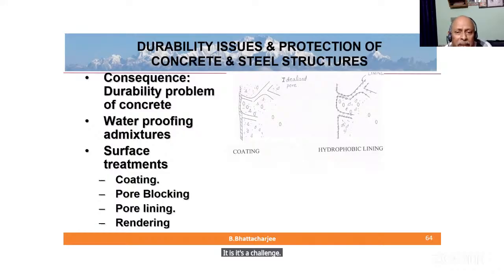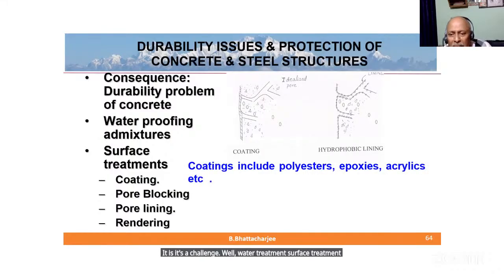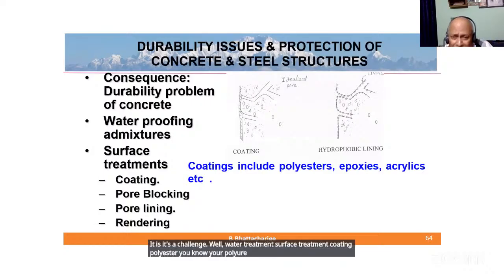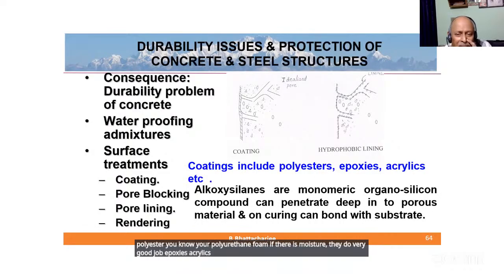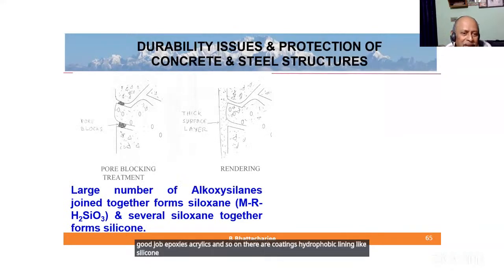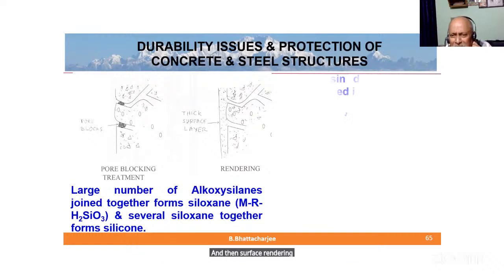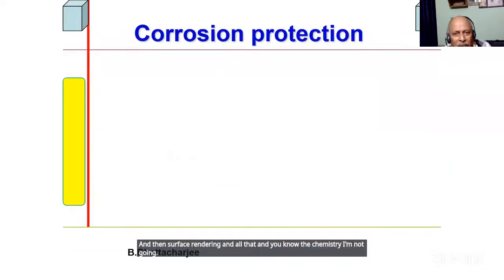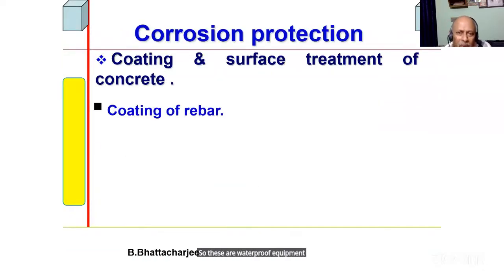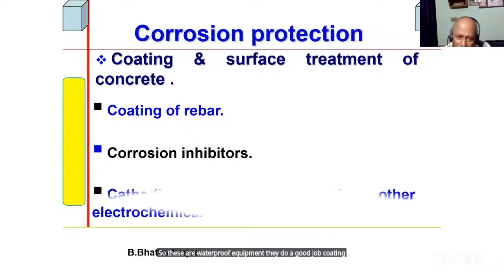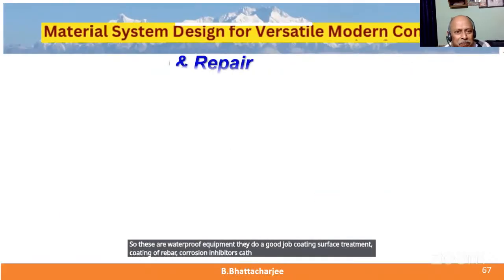Well, water treatment, surface treatment, coating, polyester, polyurethane foam. If there is moisture, they do a very good job. Epoxies, acrylics, and so on. There are coatings, hydrophobic lining like silicone, pore blockers. Even polyurethane foam might block if it gets water, and then surface rendering and all that. The chemistry I'm not going into. So these are waterproofing treatments. They do a good job. Coating, surface treatment, coating of rebar, corrosion inhibitors, cathodic protection.